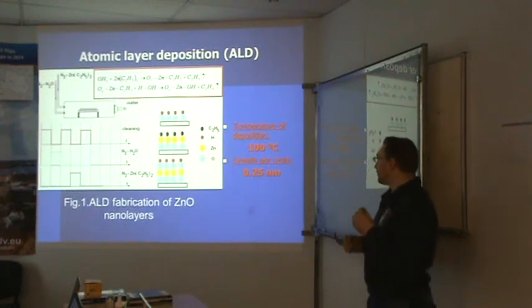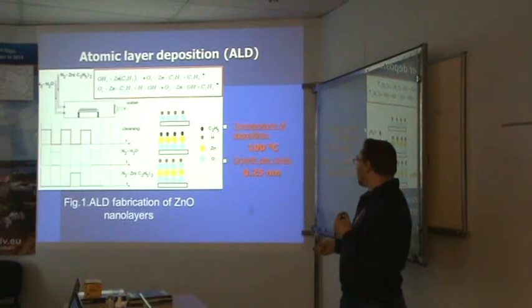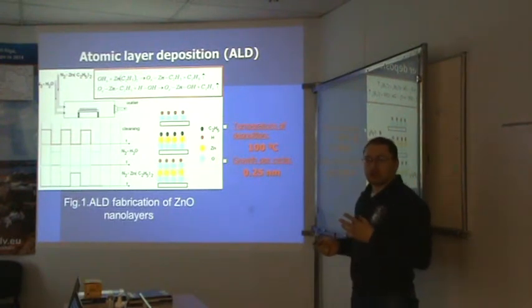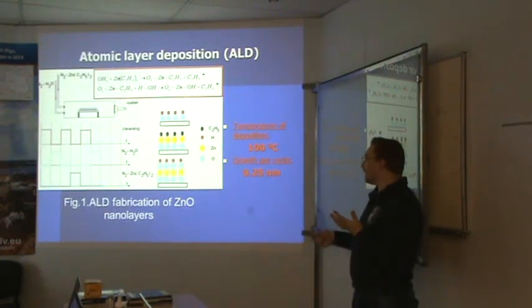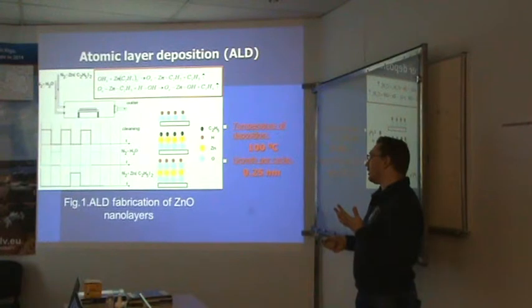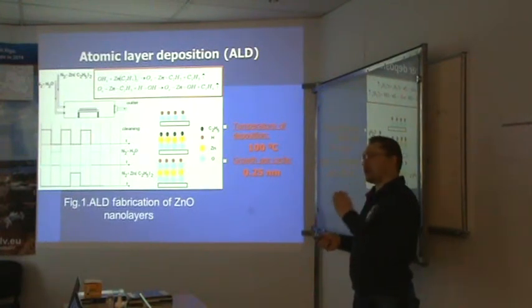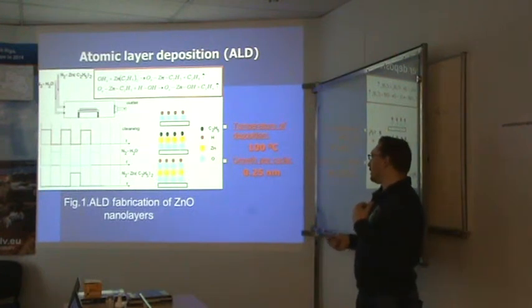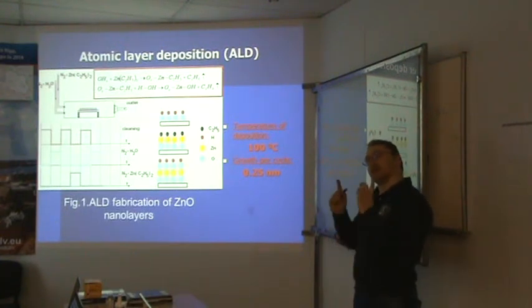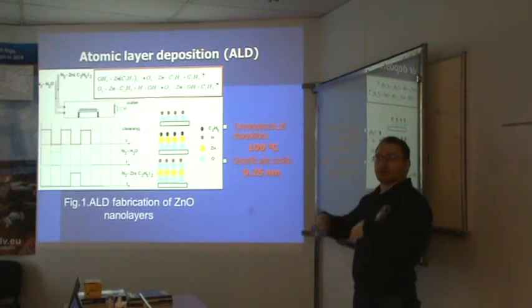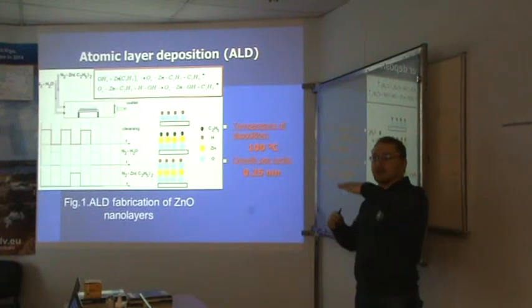Here you see the principle of atomic layer deposition. It works according to a chemical reaction. You deposit water on top of the substrate, and then using pulses of chemical precursors, you substitute the organic radicals with oxygen and OH groups. So finally, at the end, you have a monolayer of zinc oxide with OH groups on top. When you repeat the cycle, you can deposit the second layer, and finally you have continuous growth of this material.